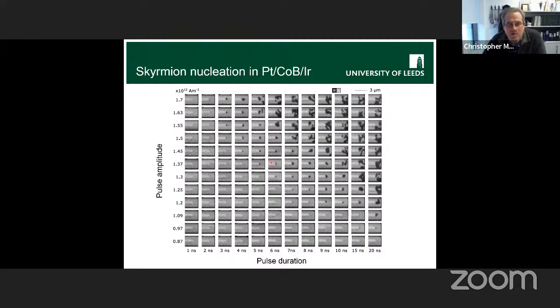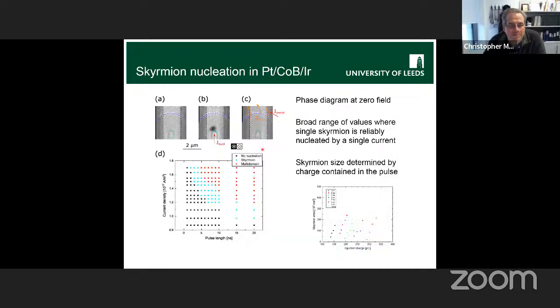And I should say this is all done at zero field. There's no applied magnetic field here, and especially in the center of this band, it's super reproducible. We call it deterministic. You really can just press a button and send in the current pulse, and a single skyrmion will appear, very, very reliably. It's just one of them, and it's always one. And so we can build up this sort of phase diagram where the single skyrmion states are these light blue dots across the middle here, where we see something like this.